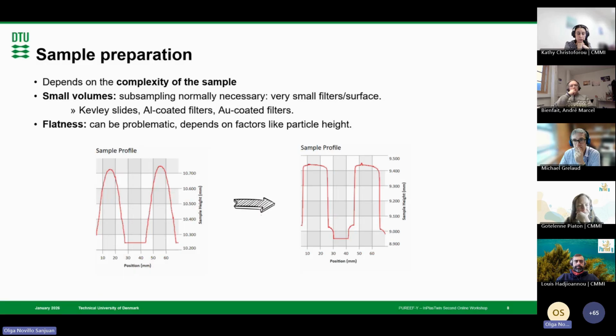Another thing that should be checked with the LDIR is the flatness of the sample. Ideally, our samples would look like the image on the right, so pretty flat. And this little peak you can see on the right corresponds to an irregularity in the surface of the filter, so particles. But if we get profiles like the ones you can see on the left, it can be problematic.